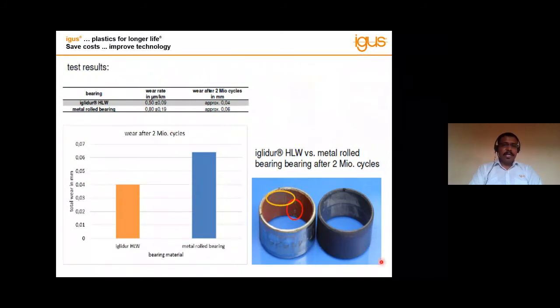As you can see in the image, iglidur HLW material is wearing almost half when we compare it with metal rolled bearing. In addition to that, metal rolled bearing has no PTFE remaining on the inner surface. In some portions you can see the metal is directly exposed, and this can damage the shaft. This can no more give a lubrication effect, and the bearing has to be changed. Whereas our iglidur HLW bearing has the same properties throughout the thickness, completely lubrication free, completely corrosion free throughout the thickness.